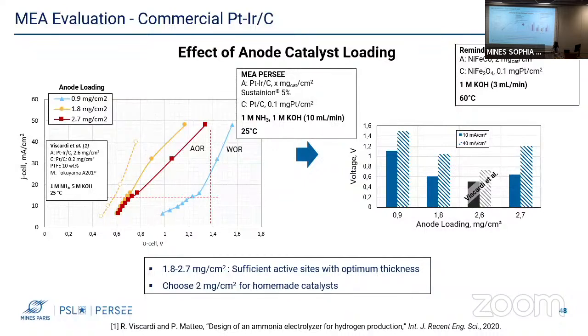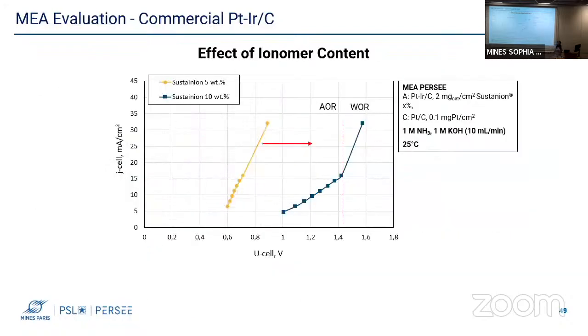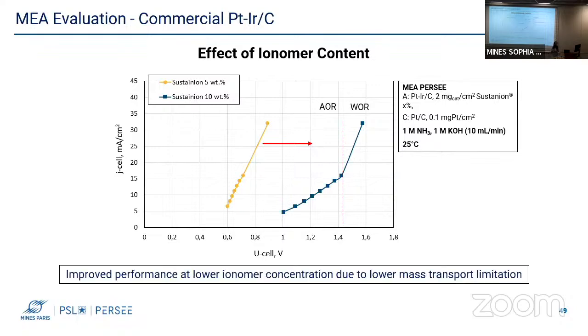For the rest of the tests, we will choose an anode loading that lies inside this range, specifically 2 milligram per centimeter square. We also studied the impact of the ionomer concentration because it has a great impact on the performance of the MEA. For this, we increased this loading from 5 to 10 weight%. Improved performance was obtained at the lower ionomer concentration due to the lower mass transport limitations that could be present at 10 weight%.